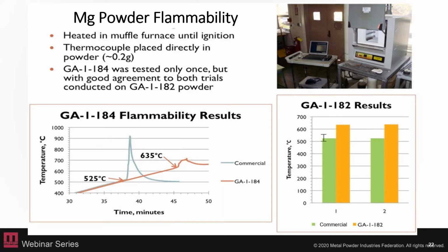And so in this case, the demonstration here is showing a heating profile of the powder in a furnace, and the commercial magnesium powder ignited at about 525, but this powder with the oxyfluoride on it didn't ignite until 635. And so that's almost the melting temperature of magnesium. And so these powders were extremely stable with that oxyfluoride coating.